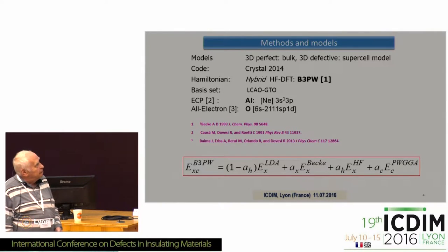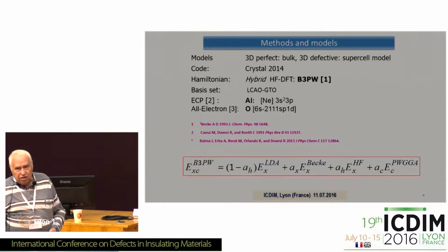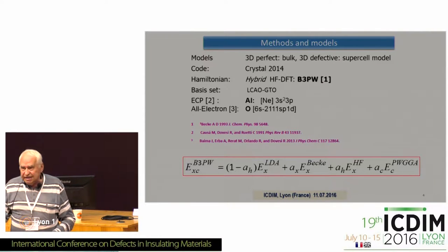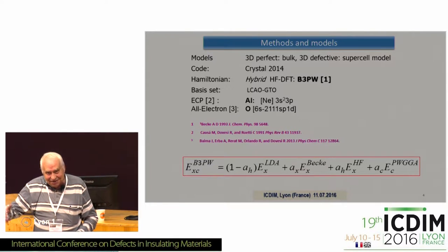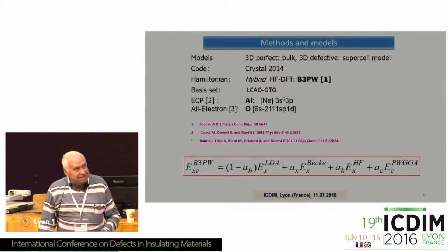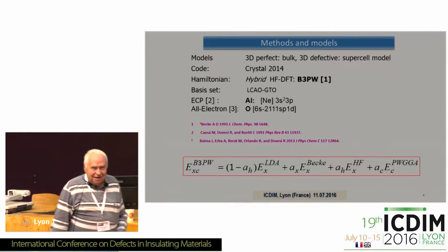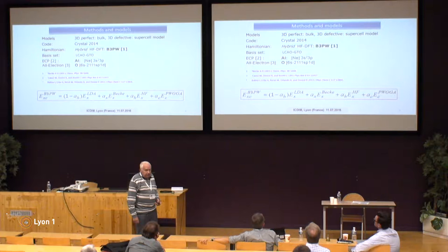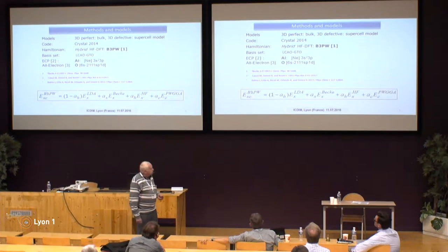In the case of Corundum, we use a hybrid Hartree-Fock DFT Hamiltonian. Nowadays saying 'we use DFT' is not enough, because DFT has many different options and the famous DFT Jacob's ladder. We use a hybrid functional because we want to reproduce the energy band gap correctly, and when you consider point defects, a correct energy gap is very important.